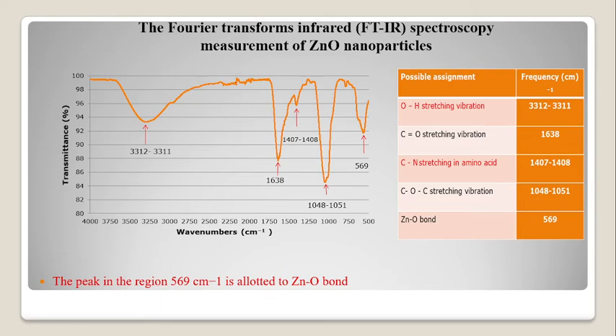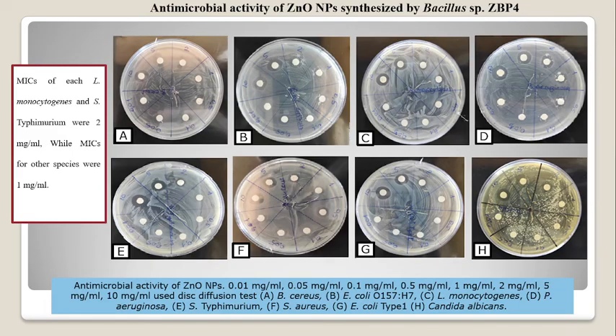As we see here, for the antimicrobial activity of zinc oxide nanoparticles synthesized by Bacillus species ZBP4, the minimum inhibitory concentrations for each of Listeria monocytogenes and Salmonella typhimurium were 2 mg per ml, while the minimum inhibitory concentration for the other species was 1 mg per ml.